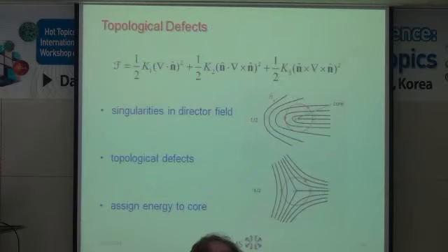Now interestingly, if one starts to look at these director fields, one finds singularities, and these are defects. So you can imagine, and I will show you some structures where these kinds of things occur naturally. Except for at this point, everywhere along here, the director field is smoothly varying, but here there's a singularity. And now it turns out that this is kind of a problem because the free energy blows up at the singularity, and it's not so obvious how to deal with this.